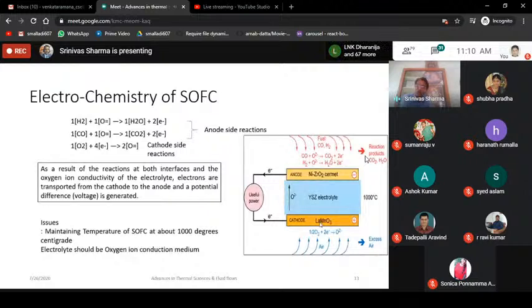And in doing so, this particular electrolyte, where it is used as a conduction medium, which is yttria stabilized zirconia electrolyte, should be at a very high temperature and it should be highly oxygen ion conductive. Here, studies have been made about thermal diffusivity of electrons from the cathode to the anode.